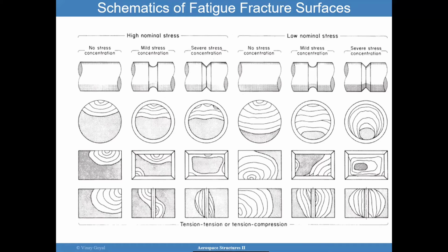So let's focus on this a little bit. I think it's worth looking at, especially if you're working on a failure investigation. This can be very valuable to you. Say you have different fatigue surfaces, and I ask you, hey, where does the crack initiate? Where does it propagate? And what does the final rupture look like? So let's focus first on the high nominal stress conditions, where you could have a no stress concentration type, a mild stress concentration, and a severe stress concentration. If you have no stress concentration and a high nominal stress, in tension loading for example, then you're going to have an initiation point, and then you're going to have your beach marks, and at the end you're going to have a final fracture.